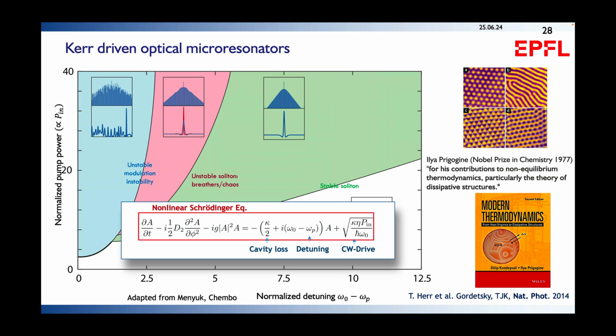Now, let me just mention that this soliton formation is truly a fascinating phenomenon in the sense that what happens in this resonator here is that you can take this nonlinear Schrödinger equation with cavity loss, detuning, and drive, and you can map out and numerically compute the solutions. And the solutions you can draw actually in a two-dimensional map. One is the power that you inject in the resonator, shown on the vertical axis, and the detuning of the laser on the horizontal. And if you compute for every configuration of detuning and power the solutions that these equations admit, you will find actually that there are regions where you have chaotic waveforms, regions where you have stable solitons, and regions where the solitons can breathe.